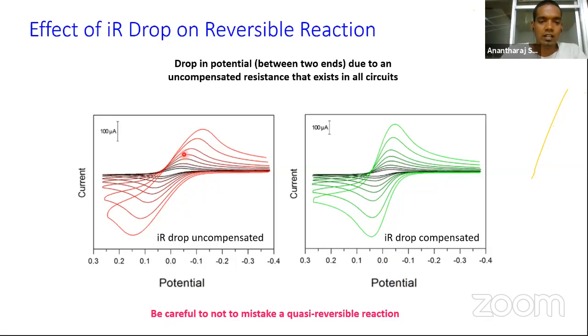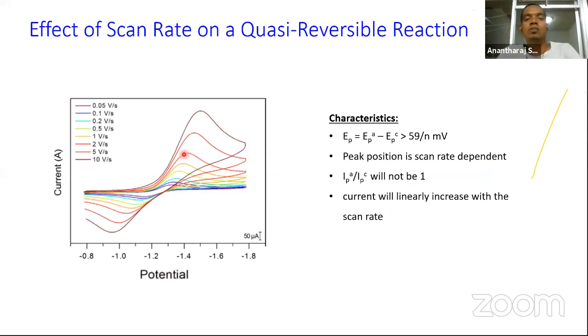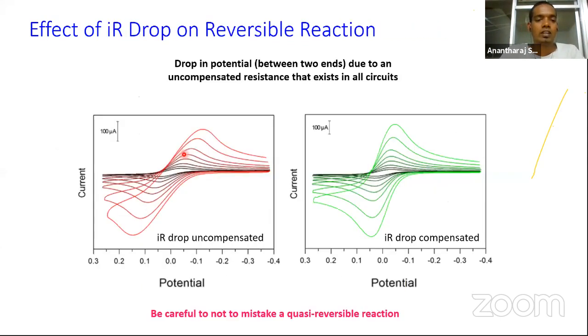This is quite confusing, right? The scan rate effect in a quasi-reversible reaction, which I have shown here, is the same as this one. So it could sometimes be problematic. We may not be sure whether the reaction is actually reversible but showing this phenomenon because of IR drop, or whether my reaction is actually quasi-reversible. In order to know this, you can do one thing: perform IR drop compensation manually. When you do that, at least at the lower scan rates, as you can see, the peak potential remains the same, which means that just by performing IR drop compensation, you can overcome the effect of IR drop. So your reaction can be said to be reversible.